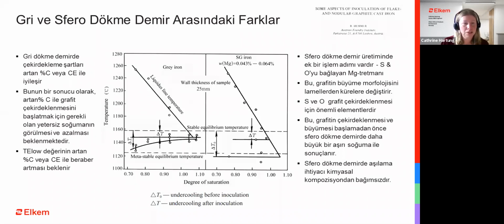But for ductile iron, the situation is a little bit different. Matthias mentioned or showed some example of magnesium treatment. And this is the differentiating thing between gray and ductile iron. To make ductile iron, you do an additional process, the magnesium treatment, which ties up sulfur and oxygen. And it does that to change the graphite growth from flake to nodules. To have the graphite growing as nodules, you have to remove sulfur and oxygen and other impurities. Now, naturally, ductile iron will also be, from the charge mix or from the charge setup, lower in sulfur. If not, you would have to add more magnesium ferrosilicon.